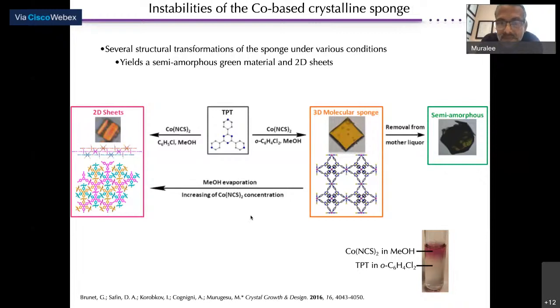Unfortunately, this is not as stable as it's claimed. So the cobalt one is basically, if you do this reaction as reported with dichlorobenzene in methanol, you can get these crystalline sponge of the reported MOF, but which quickly transform into the semi-amorphous material, which is dark green, when you remove from the mother liquor. And if you do a slow evaporation of the methanol, then you are changing into orange crystals.